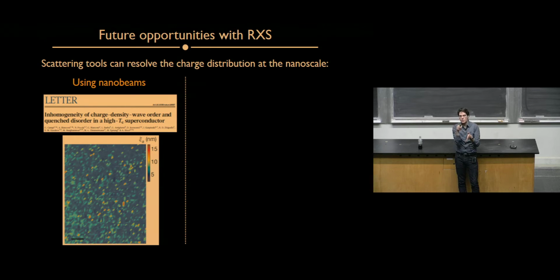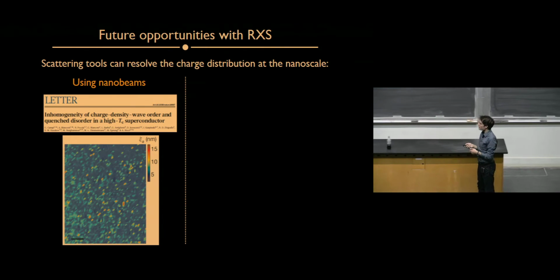And then we can sweep it across the sample and look at whether there is any inhomogeneity of your state, of your electronic order, due perhaps to that kind of phase competition that I introduced previously, right? That drives phase segregation. So there are regions of your sample that have weaker charge order, other regions of your sample that have stronger charge order. And this was done recently using diffraction, actually. So it shows that there is a very rich phenomenology in real space happening.